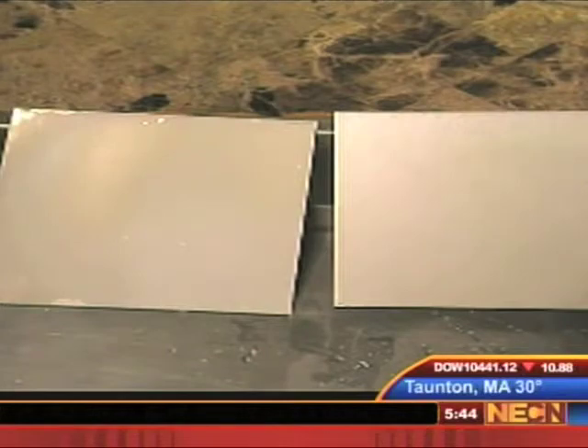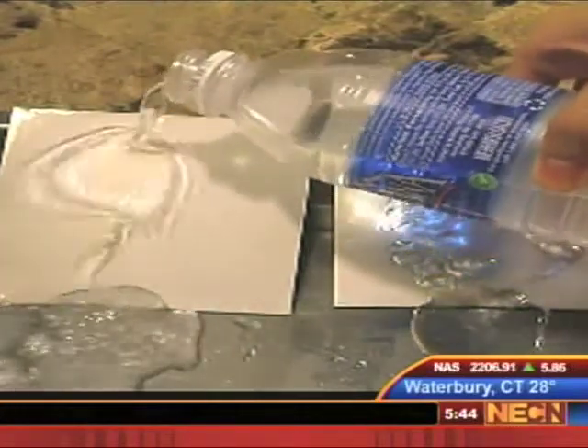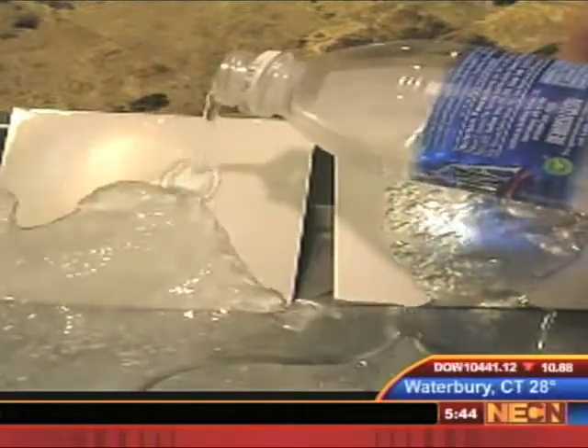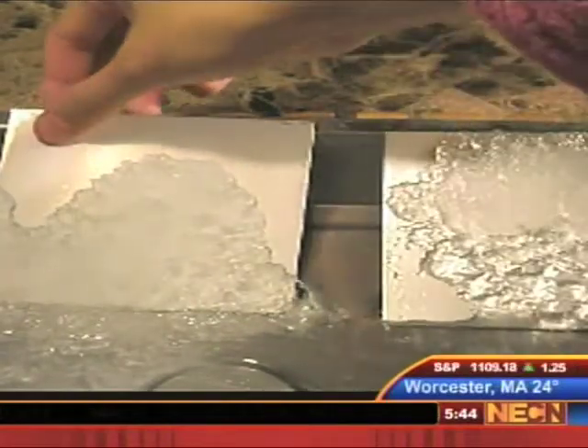On the bare metal plate, ice forms instantly as soon as the supercooled water hits it. But the plate with the nanoparticle coating repels the water. The ice you're beginning to see is just piling up from the untreated pan at the bottom. While the ice sticks to the uncoated plate, with the coated one, the ice slides right off.